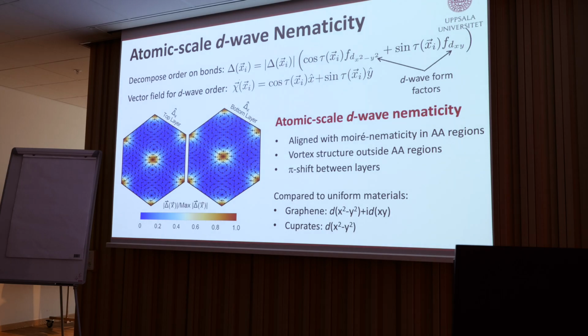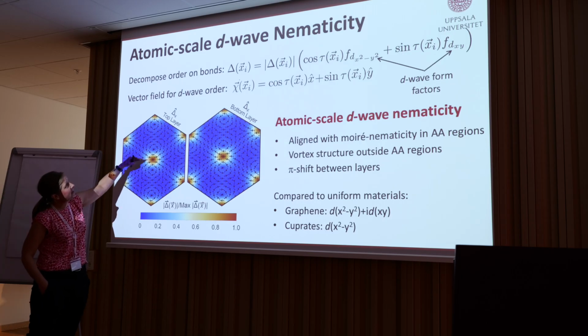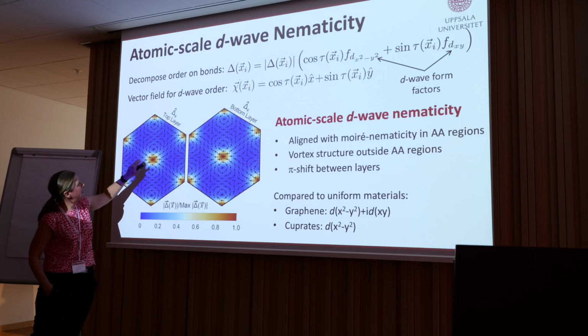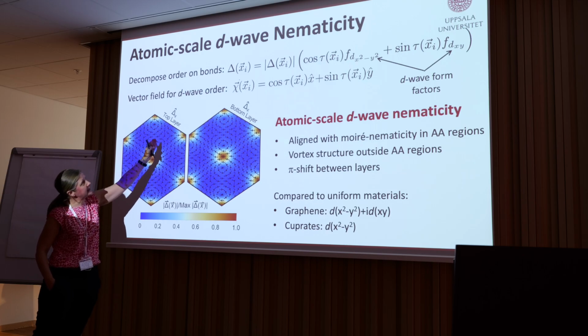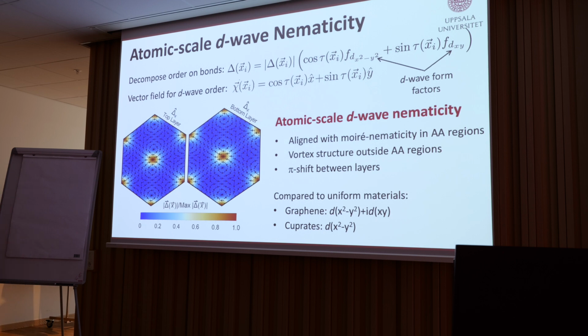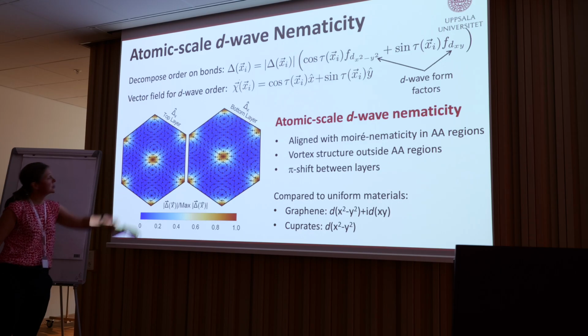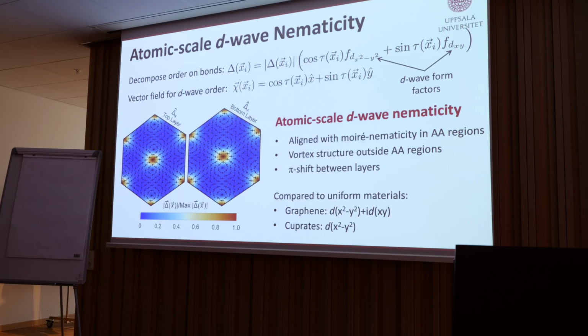Depending on how it points, it tells which type of d-wave I have locally. And we do that, and that is what these arrows I told you to ignore were. The arrows are the vector field that shows you which nematic state I have. So here, for example, you have a nematic state that points in this way. So this is dx squared minus y squared. But if you go away from this region and you point up like this, it goes, for example, up to the dxy. So I have a local d-wave order that rotates in the Moiré field, and it even forms sort of some vortex structures here. And these are not superconducting vortices, they're vortices in the nematic order parameter, the nematic vector. So there's no associated phase winding of the order parameter here.